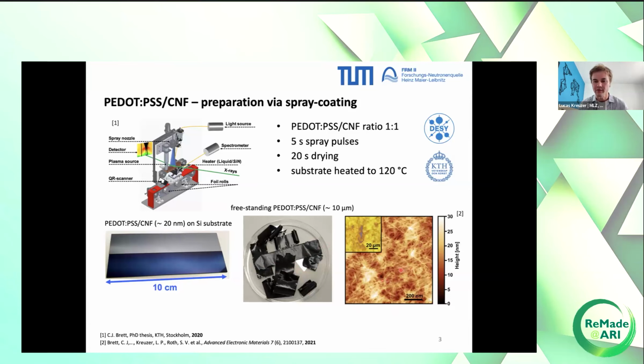So here you see an AFM image of these smaller, or thinner, films. You see here these fibrils, and the PEDOT:PSS is then dissolved in between. So a very nice technique to prepare thinner or thicker films. So an easy upscaling, let's say in all 3 dimensions, although easy would be in quotation marks because it takes a little bit of time. So these thicker films, it takes hours, I would say, until these films are prepared.